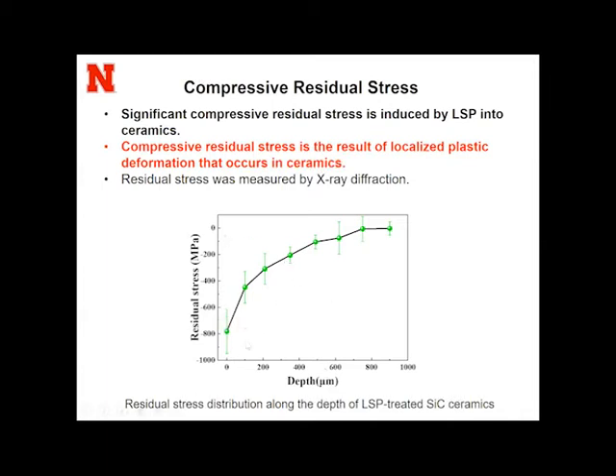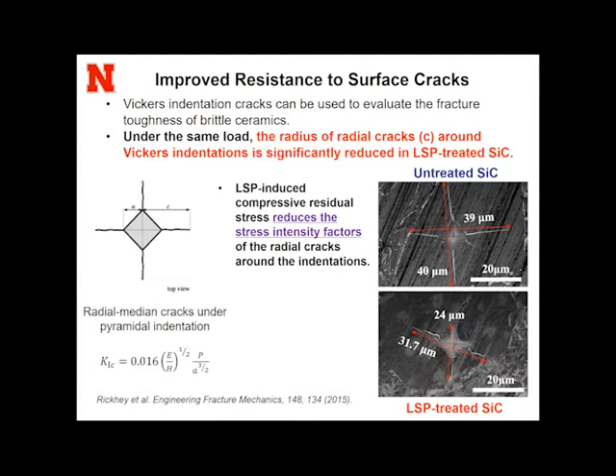We used X-ray diffraction to measure the residual stress along the depth. We see that the silicon carbide has generated a very high compressive residual stress on the surface, which can extend to a depth of 800 micrometers. Because of the compressive residual stress, this can enhance the mechanical property.